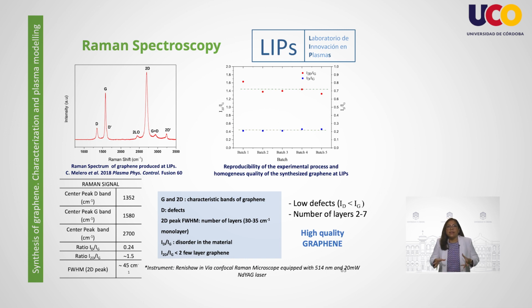We can see in this slide our results show a small value of D/G ratio combined with a 2D/G ratio higher or equal than 1, which indicates low defects and a few number of layers as indicators of a good quality of graphene, which is the case of the graphene produced at the Laboratory of Innovation in Plasmas.